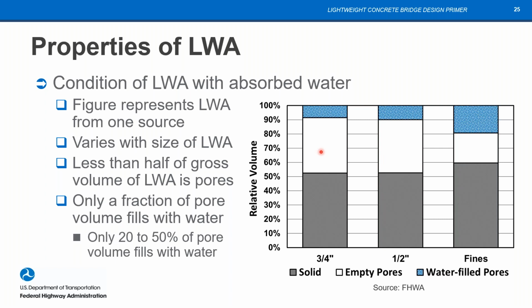So typically only 20 to 50% of the pore volume of an aggregate particle will be filled. What that tells you is that those pores are disconnected. They're bubbles that are totally surrounded by rock, and therefore water can't get to those pores. So we don't really reach a saturated condition. We don't call it that. Wetted, surface dry is what we like to use. So that's just something to be aware of, that the empty pores don't all fill up with water when you soak lightweight aggregate.